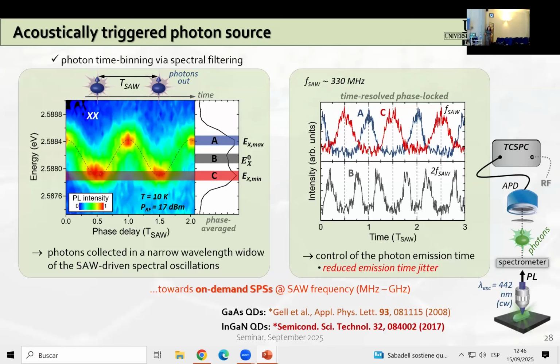This was already observed previously for other III-V quantum dot systems. And the advantage of this method is that we can produce and manipulate on demand quantum light states over a much broader frequency range as compared to other schemes. We can go up to tens of gigahertz frequencies. And also one of the main advantages is that the jitter in the photon emission time is significantly reduced, which is quite important for practical applications. So we don't actually need to use the pulsed laser anymore in order to obtain on-demand single photon emission.